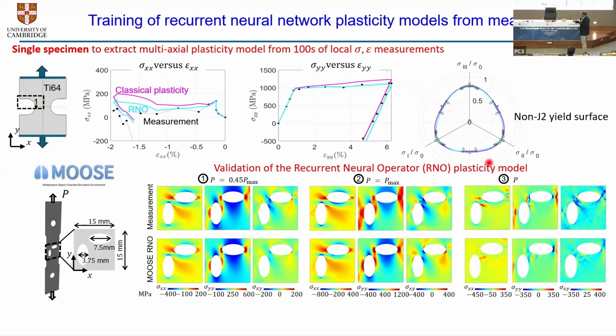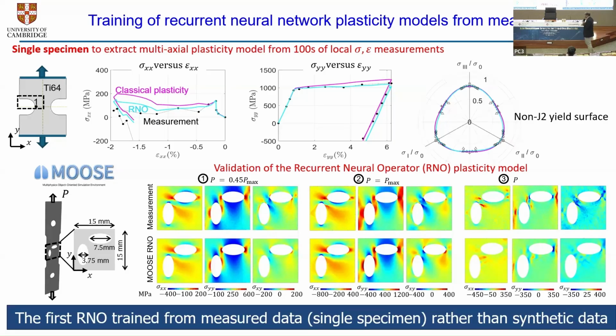So we have effectively used only one specimen, a simple notch specimen, to calibrate the model, and then we have validated the model against a rather more complex specimen. This was an autonomous framework, going from one measurement to automatically generating a plasticity model without any real intervention. And to the best of our knowledge, this is the first time that this kind of thing has been done from real experimental data using a single specimen.